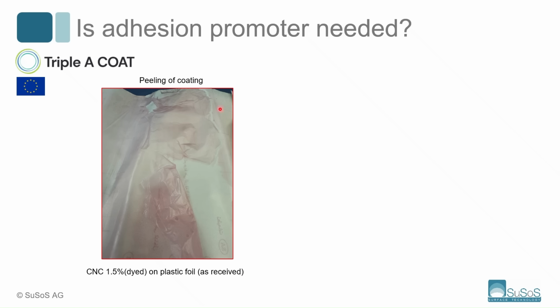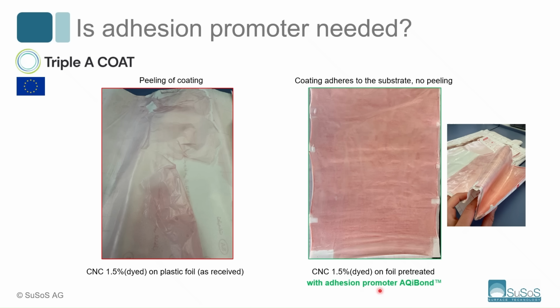However, what we observed after spraying is that if such a coating dries, we observe the peeling of the cellulose from the substrate. There is completely no adhesion. However, if we apply one of the adhesion promoters here at SuSoS and then spray the cellulose on top, we have a very good, stable coating. So the foil, the substrate, can be easily creased and manipulated without causing the nanocellulose to unglue from the foil, all thanks to the adhesion promoter.